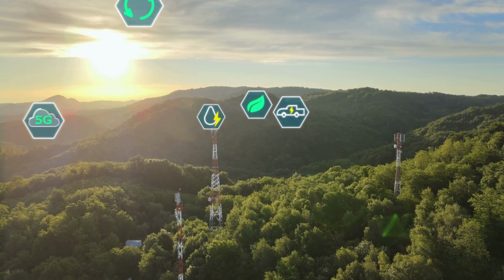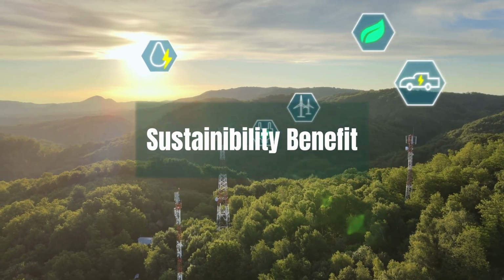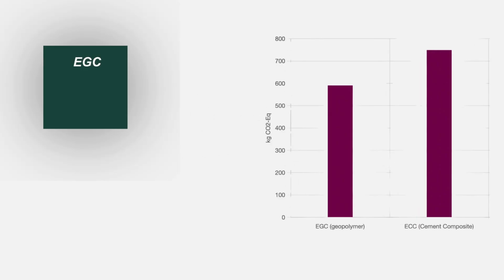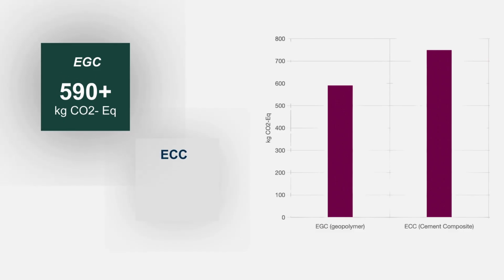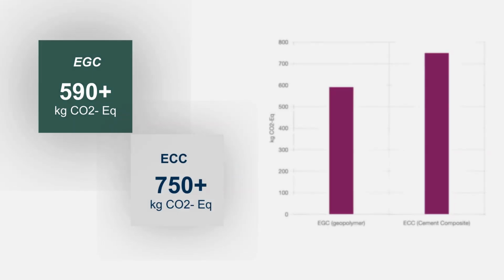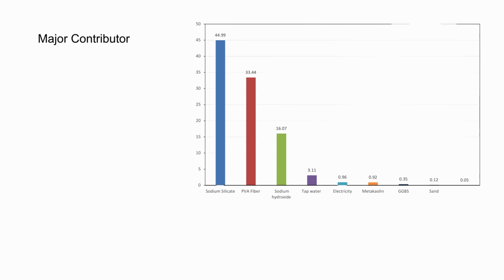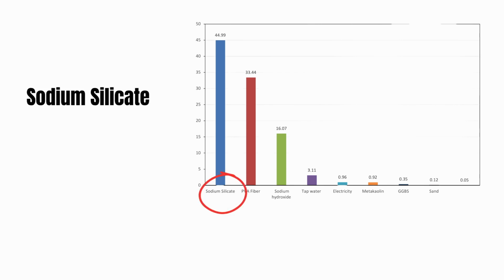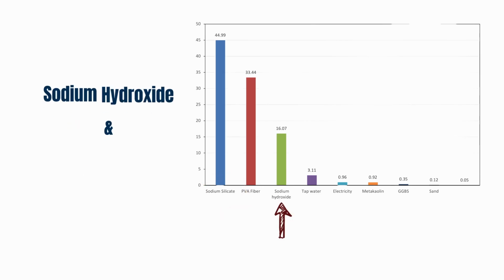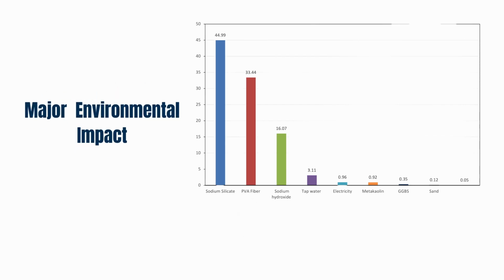EGC was chosen mainly for its sustainability benefits. It produces around 590 kilograms of carbon dioxide compared to about 750 kilograms for ECC. This reduction comes from lowering cement use and adopting a more eco-friendly activator system. A major contributor to emissions is sodium silicate. From the analysis, it accounts for nearly 45% of the total carbon dioxide, making it the largest source. Along with sodium hydroxide and PVA fiber, it forms the majority of the environmental impact.